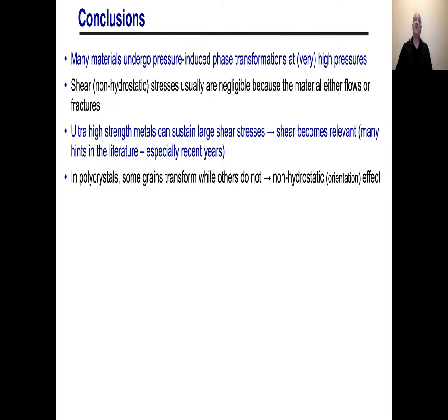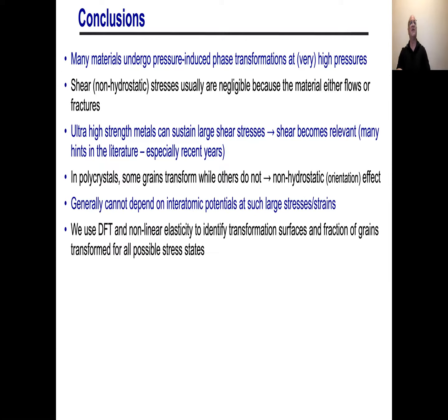In polycrystals, one of the interesting things is that some grains will transform under a given stress and some will not. Well, that's just because, unlike pressure, shear stress depends on the orientation of the grain relative to the shear axis, the particular orientation. And so some grains will be more favorable than other grains. And that can only happen if it's a shear-driven effect, not a hydrostatic stress-driven effect.